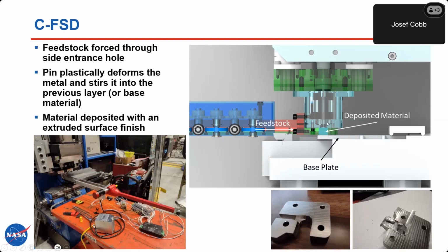So the process, we'll start down here in the bottom right-hand corner. So this is actually what sets the shape of your deposition for the conventional friction stir deposition. So you can see here's a die, which is in reference to the model of what's with the feeder and everything on it right here. It's this green part on both sides of the deposited material. And we're feeding in a feedstock. So in this case, we're using a square feedstock that we're feeding into. There's a pin that comes down here in the center that's rotating.